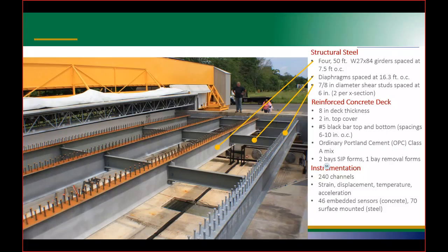Thank you, Sagata. So as Sagata mentioned, the first specimen's construction was finished in the summer of last year. We gave it 30 days for the deck to cure before we commenced any testing. The specimen itself was designed using the 7th edition of the AASHTO LRFD bridge design specs. It's composed of 4 rolled steel girders. Each has a different metallized coating. So that's a hot dip galvanized, 100% aluminum, inorganic zinc, and then an 85-15 zinc aluminum blend. It has an 8-inch thick cast-in-place deck with number 5 black bar reinforcing. In 2 of the bays we used stay-in-place forms, and in 1 other we used removable forms just to compare the performance.